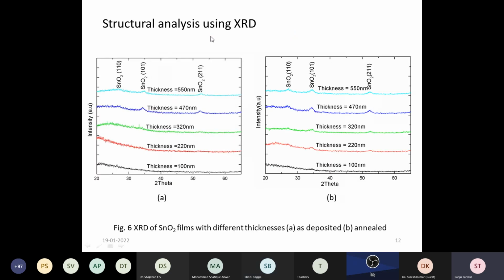Next, we do its structure analysis. Most of you know what structure analysis is. We do structure analysis to see in which direction our film crystals are oriented. For XRD, we used different films deposited for 10 to 50 minutes, with thicknesses of 100 nanometers, 220, 320, 470 and 550 nanometers. We made two sets of experiments, without annealing and with annealing. Here we can see that as we anneal the film, the sharpness of the peaks increases. Sharpness increasing means its grain size is increasing. We can see it using the Debye Scherrer formula.